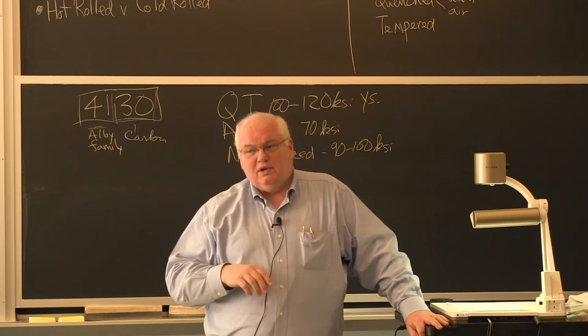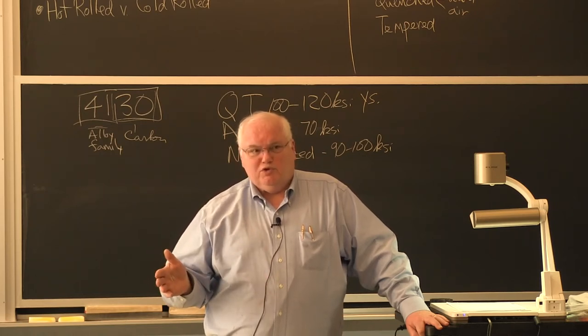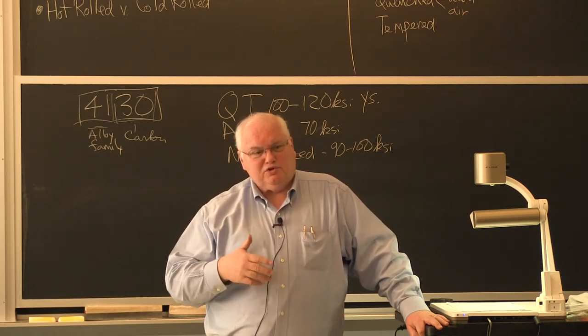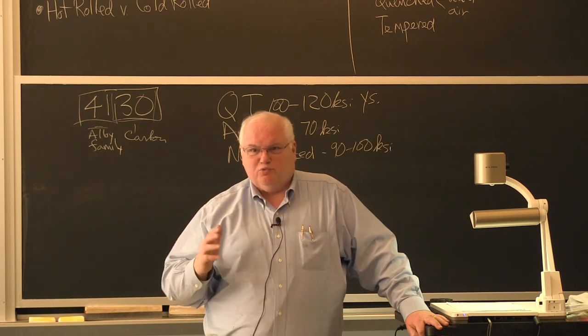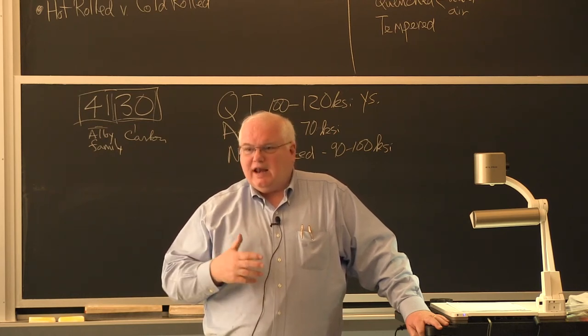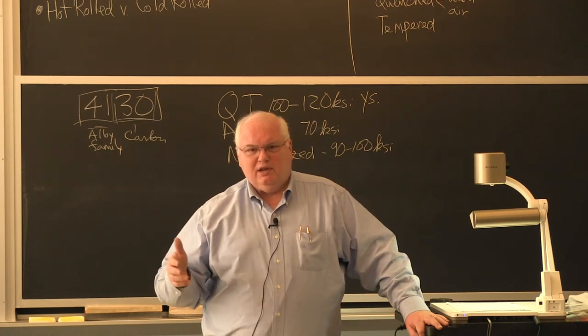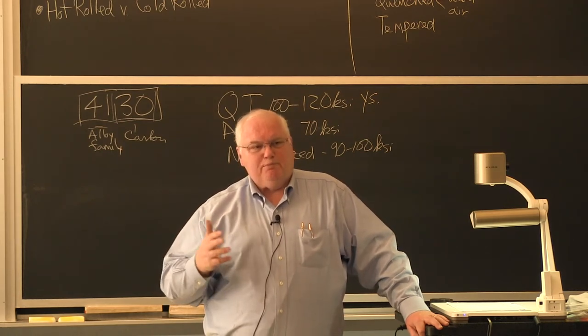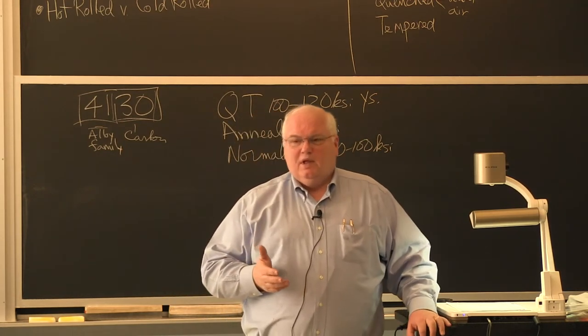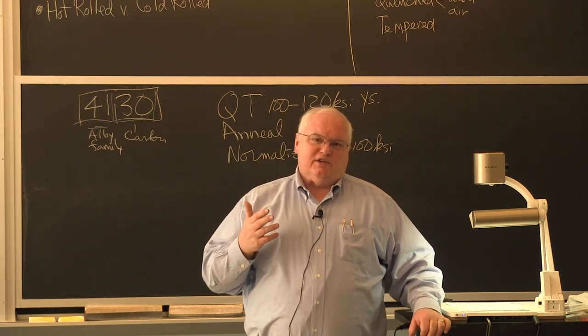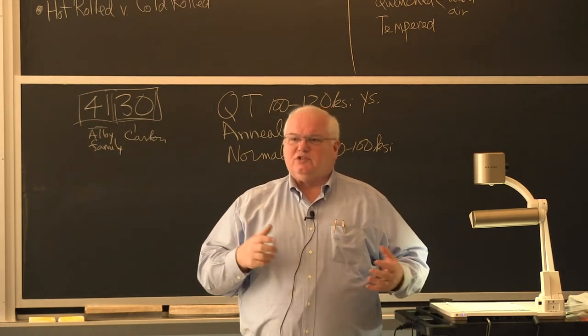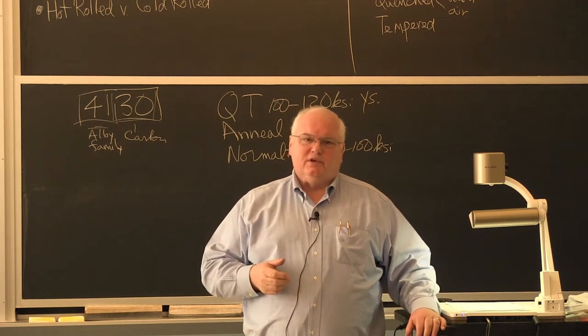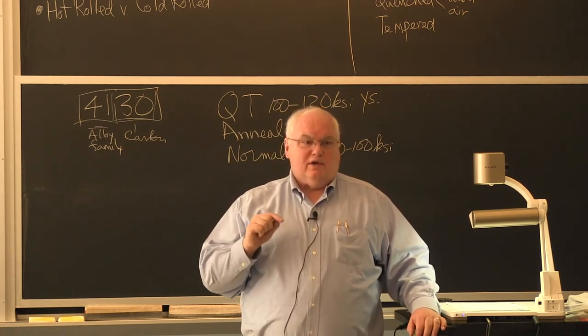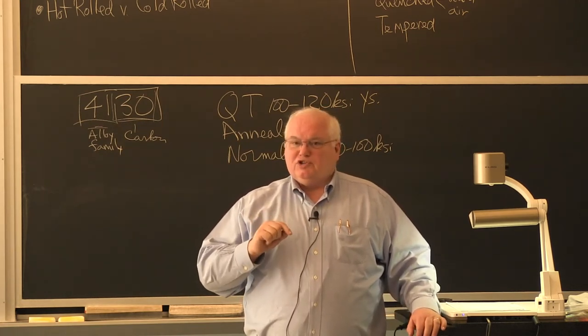And what had happened? Someone electroplated it. When you electroplate the steel, you introduce hydrogen. The steel's embrittled. If that thing gets shipped to him and whoever did it didn't bake out the hydrogen, and the steel's embrittled and it starts getting stressed within a few days or a few weeks, you have a brittle material and it can start a crack.